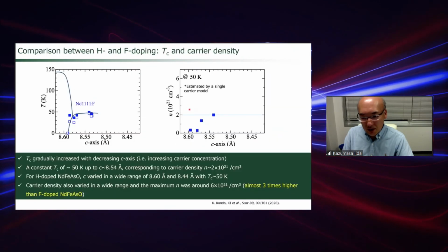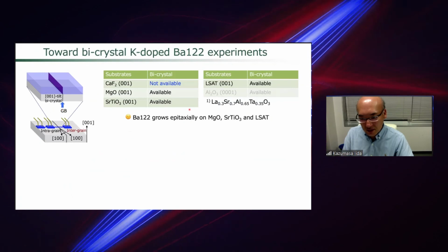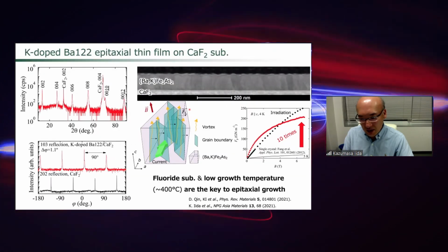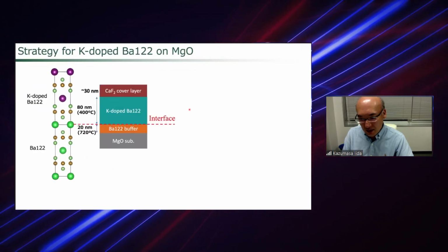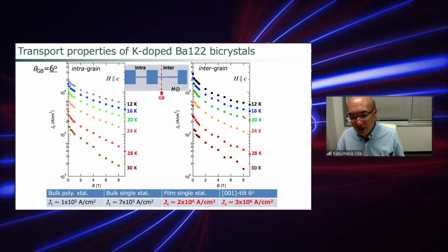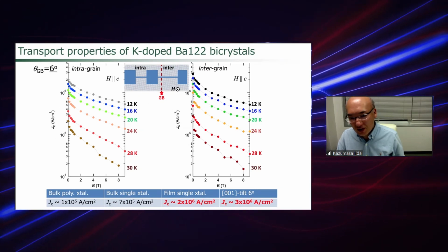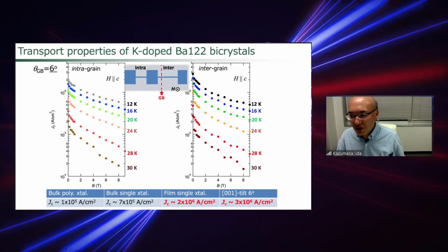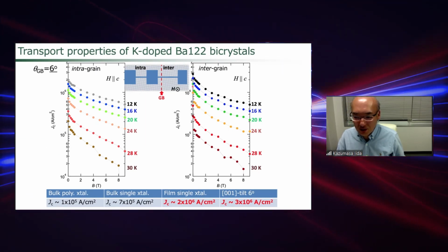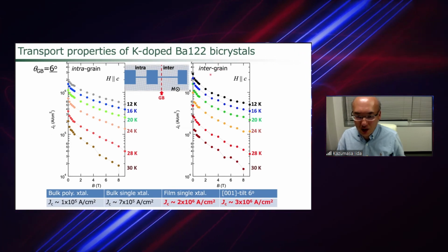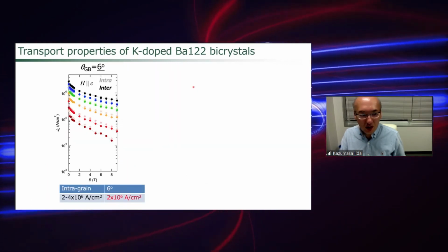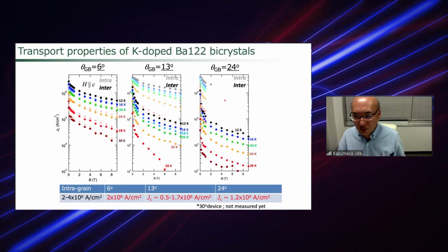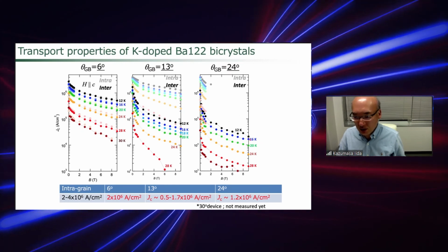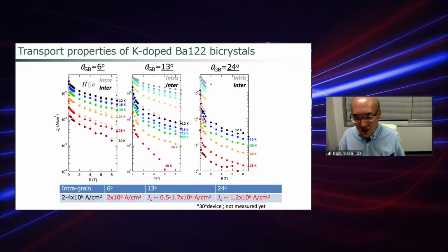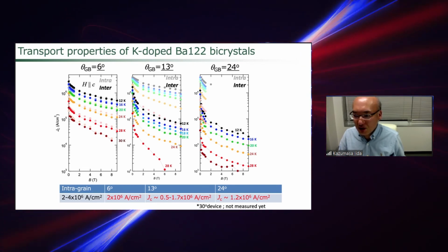For this one, even at 20 Kelvin, the Jc is over 1 mega ampere per square centimeter. So that means the single crystal, or even the sample containing grain boundaries, is quite large. But of course, this is not a fair comparison. For example, for this one, with a grain boundary angle of 24 degrees at 20 Kelvin, the Jc is still over 10 to the power of 6 ampere per square centimeter, which is almost comparable.